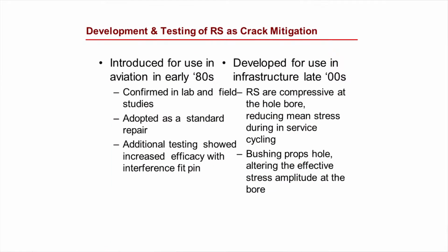As I said earlier, this was introduced in the early 80s for crack repair for aviation, with additional testing showing that if we put that interference fit pin into the hole, it would make it even better. And then in the 2000s, we started looking at this for structural steels for infrastructure. We found that that residual stress is compressive at the hole bore, reducing the mean stress during in-service cycling, which is obviously very helpful for crack arrest on your structures.